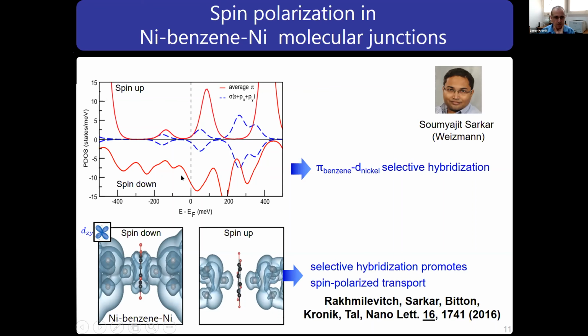And you can see that close to the Fermi level, which is what would dominate spintronics, you really have a large spin polarization. So the average spin down of pi electrons is not the same as the average spin up. And in fact, if you take a small window around the Fermi level and plot the actual orbitals there, you'll see that the spin down orbital really builds a bridge from one nickel to the other through the benzene molecule. So you can expect reasonable conductance. Whereas in the other spin channel, you don't even see a continuous distribution. So it's not surprising that you would have spin polarized transport. And it is clear that it is entirely brought about by this selective hybridization process.